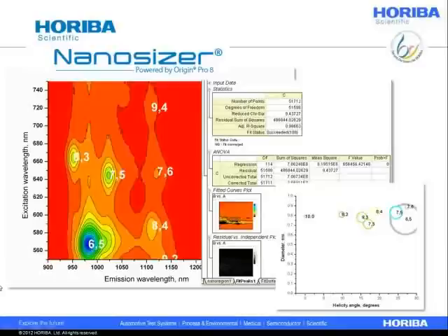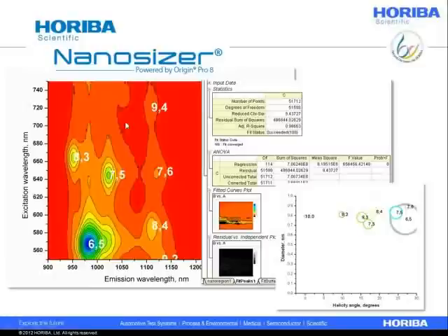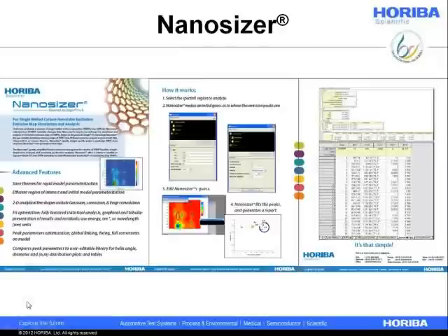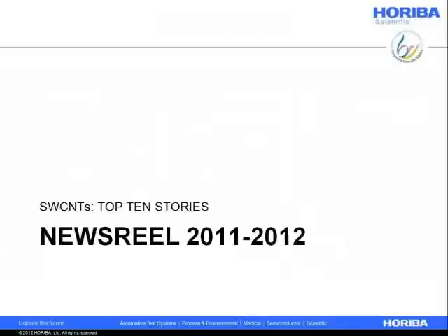We've followed the model developed by Weissman for identifying single-wall carbon nanotubes and have a software package that allows structural assignments for individual carbon nanotubes. It's based on a nonlinear least squares fitting algorithm, licensed to Origin Laboratories. With this software, you can make sub-nanometer particle diameter size measurements in addition to length distribution and helical angle distribution — a valid way of characterizing the helical, chiral, and length-dependent properties of individual carbon nanotube preparations that has met with significant market acceptance.